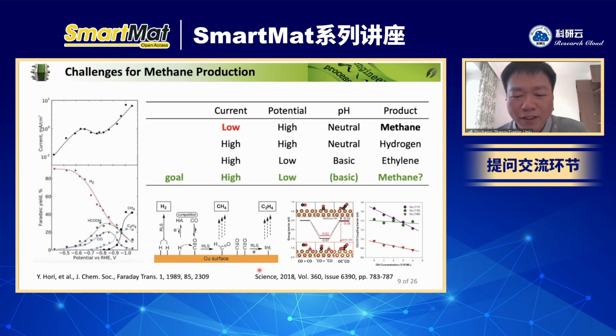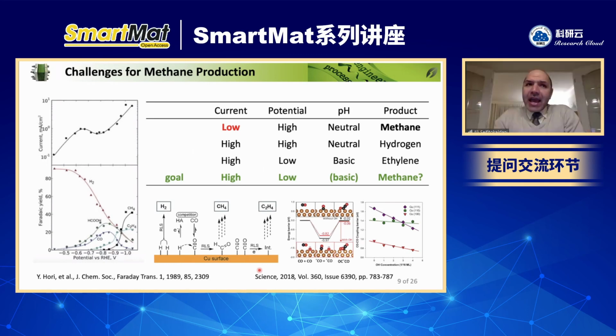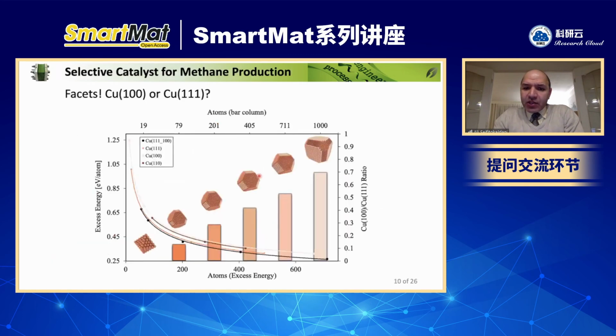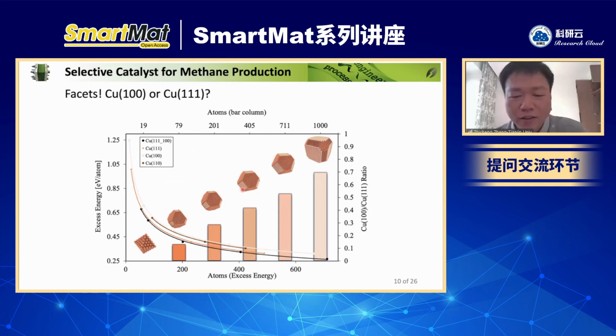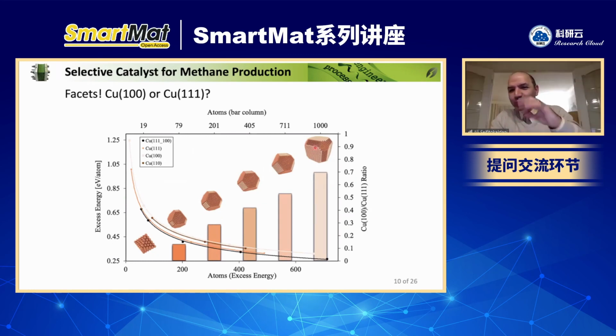So in this way, the boundary is very important to promote the formation of the CC coupling for this process. Exactly. Yeah, no, I agree with you. And I guess those grain boundaries are important. Most likely the reaction happens mostly in those boundaries. And if you have larger particles, then you provide more grain boundaries. And then also the CO, let's assume that CO is the critical reaction intermediate for CC coupling, and then you provide larger opportunity.